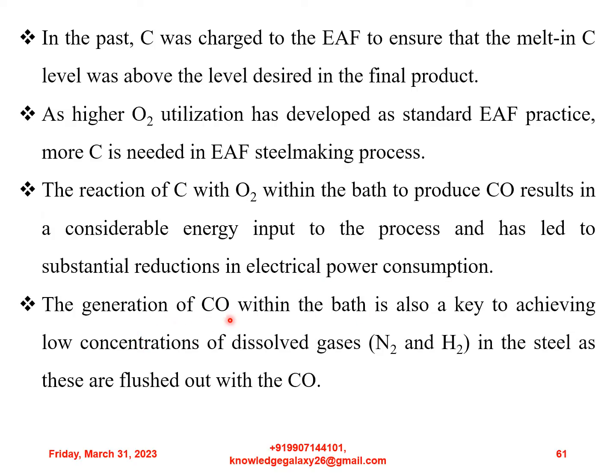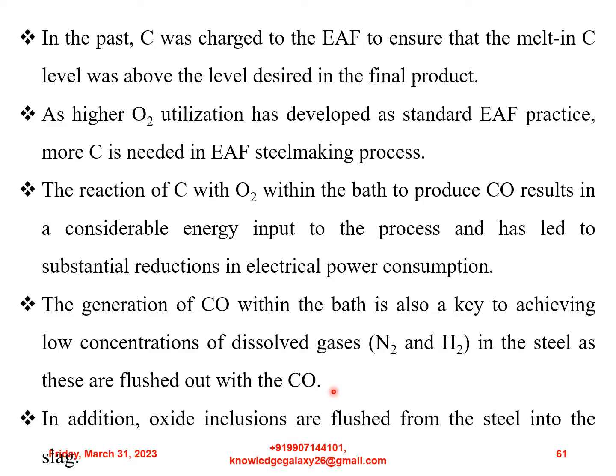The generation of CO within the bath is also a key to achieving low concentrations of dissolved gases, that is nitrogen and hydrogen, in the steel, as these are flushed out with the CO. In addition, oxide inclusions are flushed from the steel into the slag.